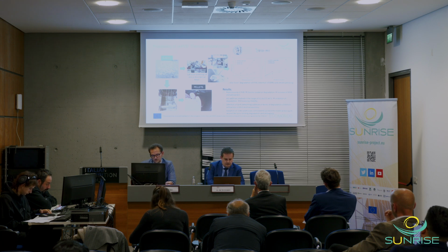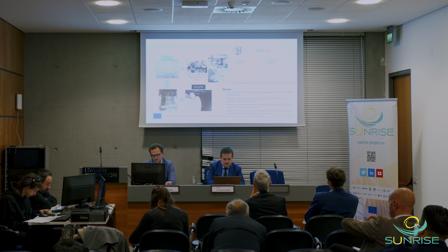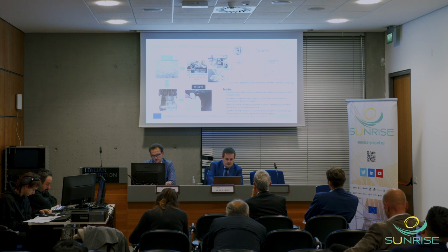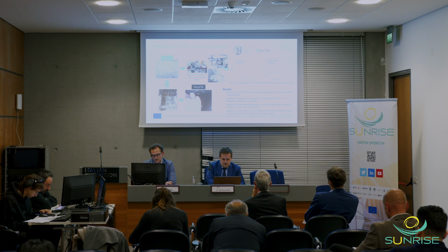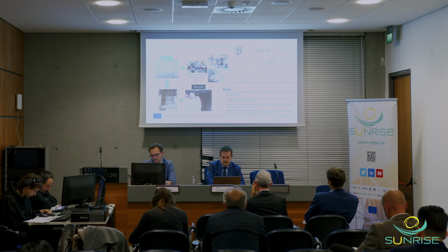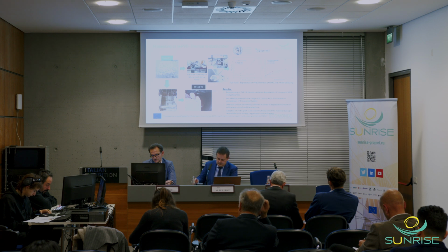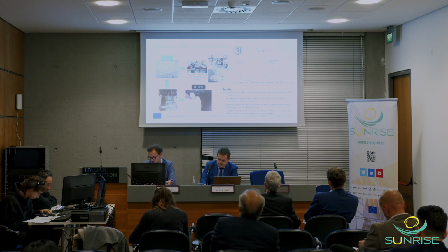What happens here is that in this process of extruding the PVB, there is going to be a new thermal degradation, and also in the posterior use there could be this thermal degradation. So the partners have been working on antioxidant additives to avoid the chain scission mechanisms created by the thermal degradation, inhibit this and allow a new life for this PVB. Working with very low quantities of antioxidants, it has been possible to inhibit this degradation, and this has also been done at pilot scale, including the antioxidants in the production of pellets for after that film.